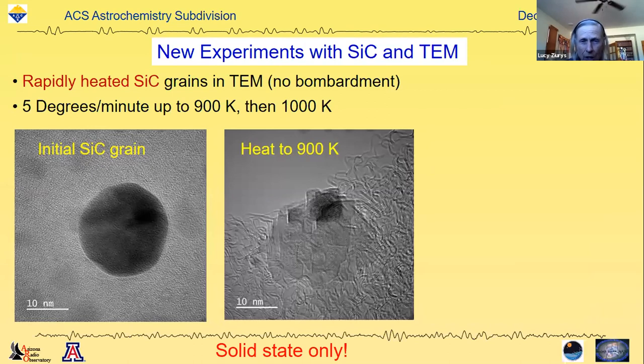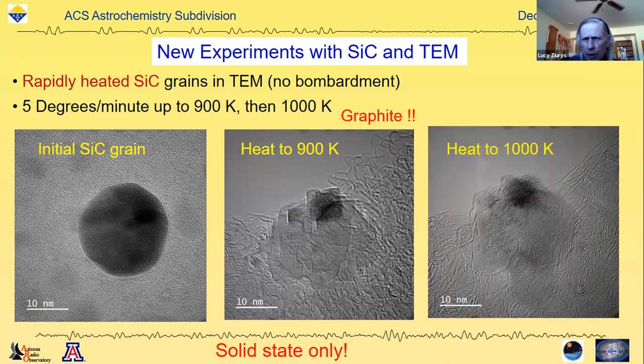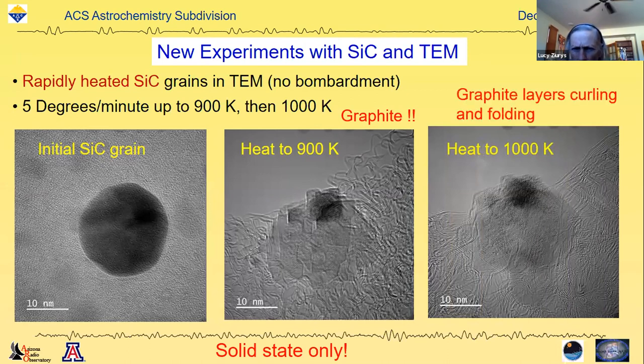And you can see that the grain has changed completely. There's a little silicon carbide left in the dark black. And you see all of the spaghetti-like structures, which are graphite layers forming and distorting. And we actually took that up to 1000 degrees. And here you can see the graphite layer folding and forming loops, and basically the silicon carbide is pretty much gone.